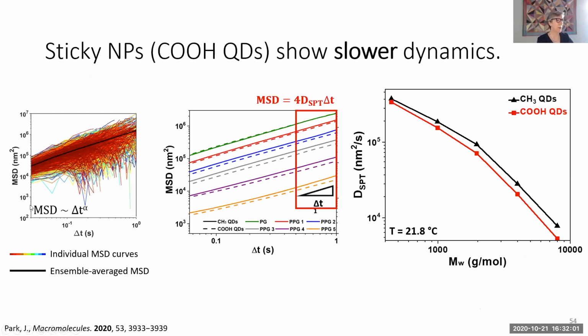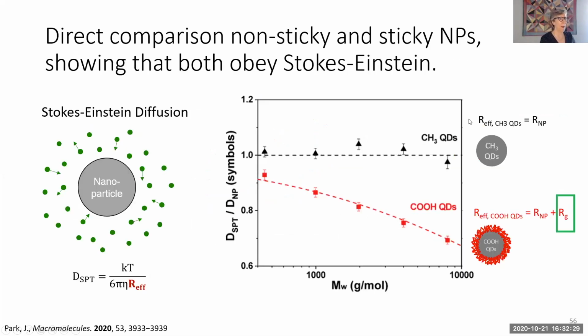So there's the mean squared displacement as a function of time interval. And this is for different molecular weight polymers. And you can see out at these long times, we have nice diffusive behavior. And as we were hoping, we saw two different diffusion coefficients. We saw a measurable difference in the diffusion coefficient for the sticky and the non-sticky particles. And so the sticky particles have this adsorbed polymer chain on it.